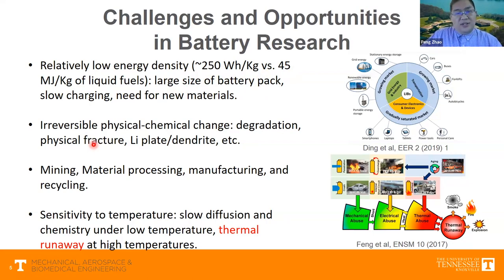And the second thing is, unlike engines that can serve us for decades without a problem, batteries are inherently subject to irreversible physical chemical change. We typically call this degradation. This degradation can include the loss of active materials, the formation of physical fracture in the particles, and also the lithium plating and dendrite that can be formed under high rate charging or low temperature charging conditions.